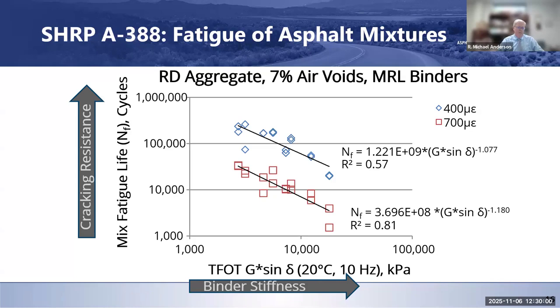The other important part is something we always talk to folks about. You remember when I said at the beginning, it's not all about the binder properties. You just want them to do their job. Part of it has to do with the pavement thickness. What affects strain in the asphalt mixture is the thickness of the pavement. So the blue cases up here are a lower strain, representing thicker pavements, than the red, which represents thinner pavements and a higher strain overall. You get a whole lot of bang for your buck just by reducing the strain in the pavement itself, even more so than what you can get out of the mixture stiffness and how that changes as a result of how the asphalt binder stiffness changes.